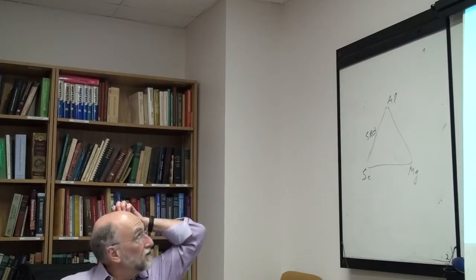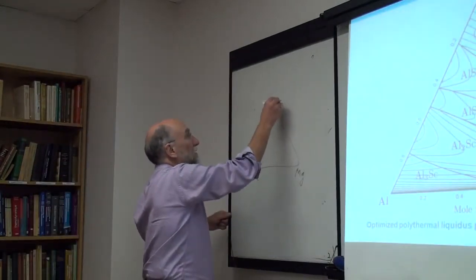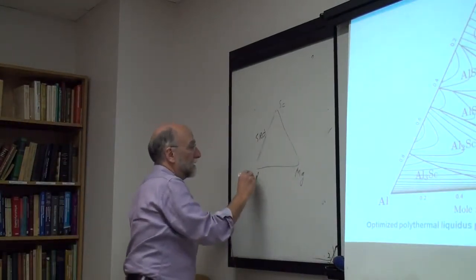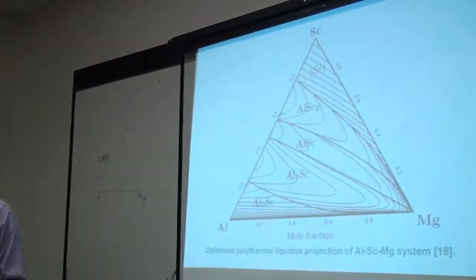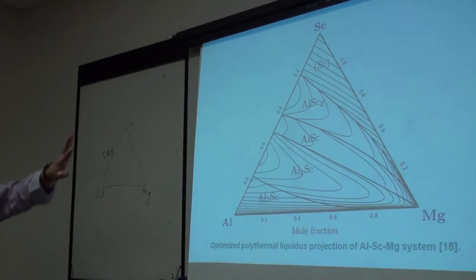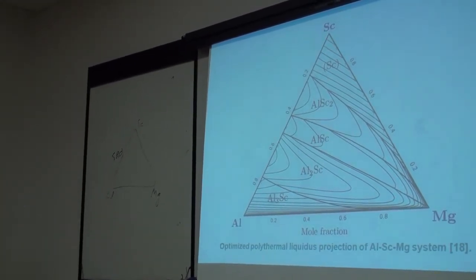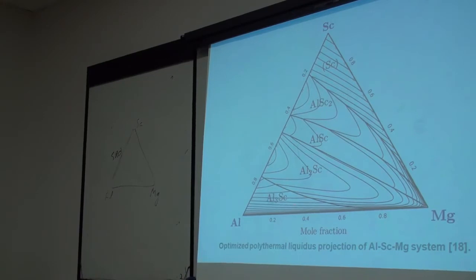Okay, I did it the other way around here, so let's do it this one. And this is very typical of this type of solution. The phase diagram, this is the Liquidus projection. So you look at this system, this is the Liquidus projection. Here it's calculated, but this is what the measurement looks like. So these two systems are quite ideal, and this system is quite negative with a very strong ordering.